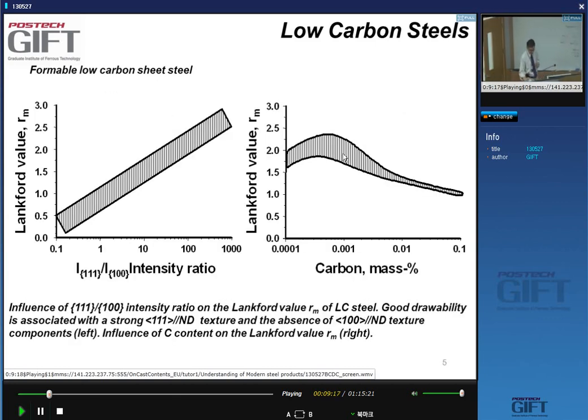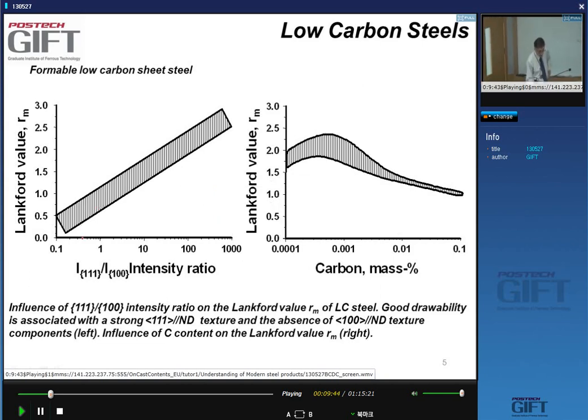All right. That's one thing. The other thing that is important, and we already know this, is the fact that to achieve high formability, we need to have a high R factor. R, and this R value, it can be expressed as the mean R value. And what we know already is that we need to have a so-called fiber texture. Now, if we have flat rolled products, we need to have 111 direction parallel to the normal direction. Yes, that's this fiber, right?